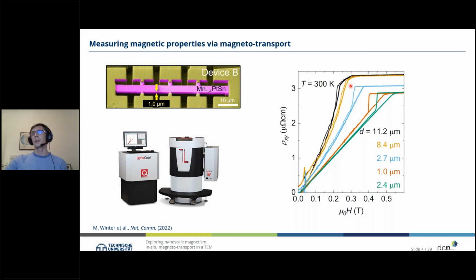But if you go to smaller thicknesses, you see some loops popping up, and the question arises: what are these loops? What different magnetic states arise here? And this is quite hard to tell if you simply have only such a measurement. And it also shows us that the sample geometry has a strong impact on the magnetic properties.